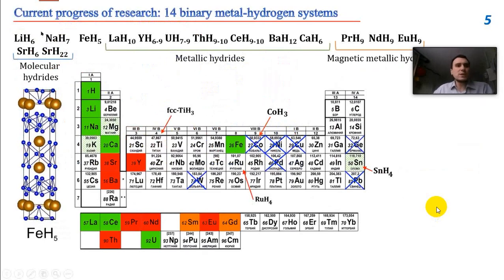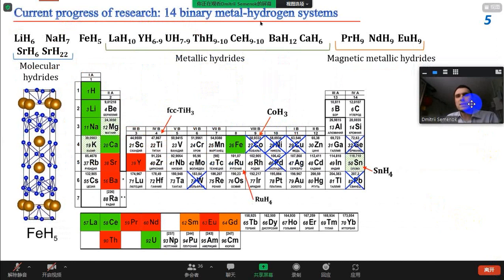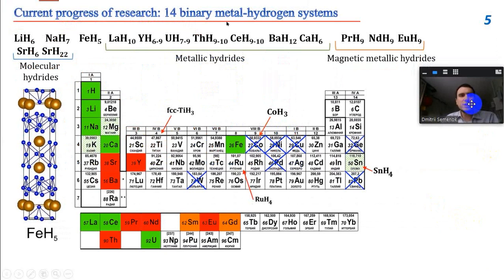So at this moment, about 14 binary metal-hydrogen systems have been investigated under high pressure, and a lot of unique, interesting, unusual hydrides were synthesized, such as molecular polyhydrides of lithium, sodium, strontium, iron, metallic polyhydrides of lanthanum, yttrium, uranium, thorium, cerium, barium, and calcium, and magnetic metallic hydrides, which should demonstrate magnetic properties according to theoretical calculation. These are praseodymium H9, neodymium H9, and europium H9. So those are the 14 binary metal-hydrogen systems. You can see it on this slide, on this figure.